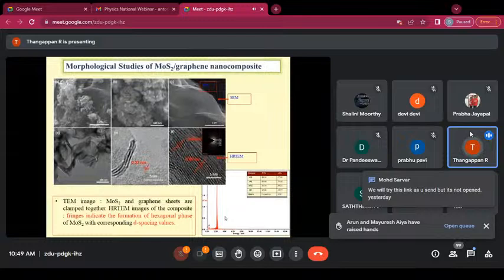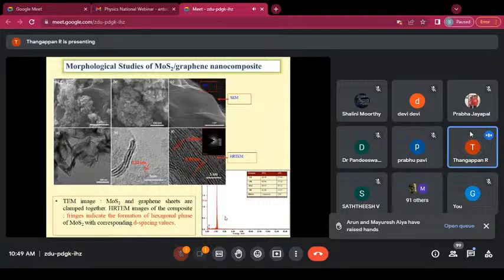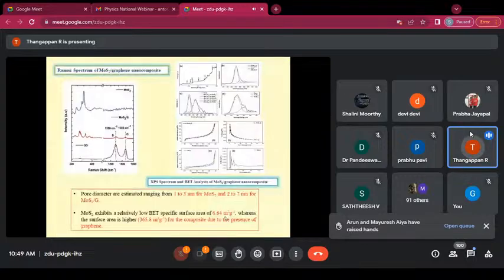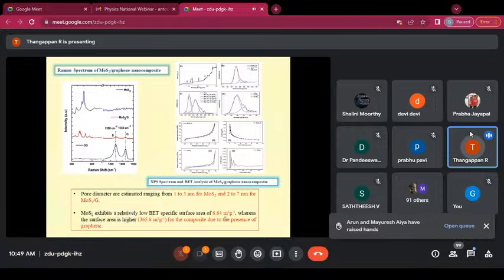The same figure shows the morphological view of the material, and at 5 nanometer magnification, the lattice spacing pattern of the material. Raman confirmed the carbon material and the molybdenum sulfide material, and XPS was run. Then we calculated the pore size and pore volume of the material, 1 to 3 nanometer pore diameter, and then 2 to 7 nanometer for the composite material, and a high surface area is achieved for the composite material.